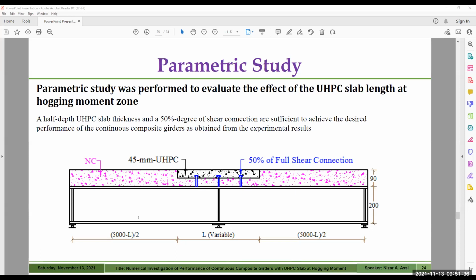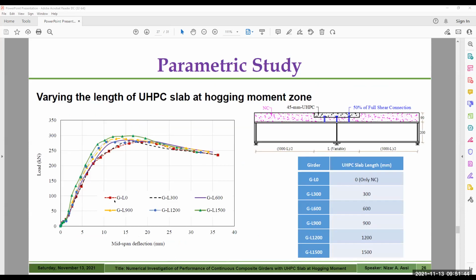As you see, the red curve, which represents the load displacement curve for the girder with no UHPC slab, we have very low stiffness compared to the green girder, which was constructed using UHPC slab with a length of 1500mm. So within the elastic range during this early stage of loading here, as increasing the length of the UHPC slab, the stiffness of the beam will increase significantly.